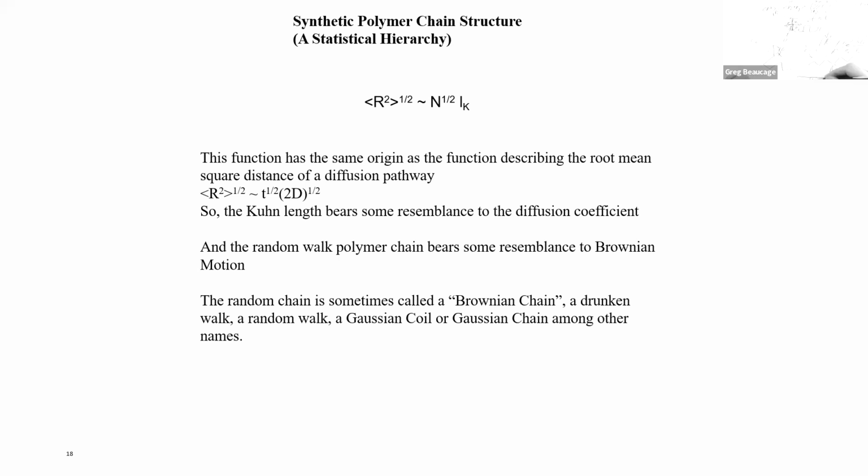That means this has to equal N times L chemical times C, the coefficient that translates it. So that means the C has to be like L K over the chemist number, and that's 7.6 for polyethylene. So you can measure it. No, it's not an empirical number. It's an actual number. You can look in the Polymer Handbook or maybe the NIST webpage, and they'll give you C infinity.